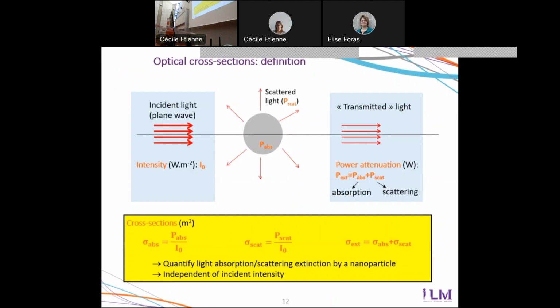So cross-sections are just the ratio between absorption, scattering, or extinction, which is the sum, powers, divided by the intensity of the laser beam. So they are surfaces, and they are independent of incident intensity, at least in the linear regime, and they quantify how strongly a nanoparticle interacts with light.